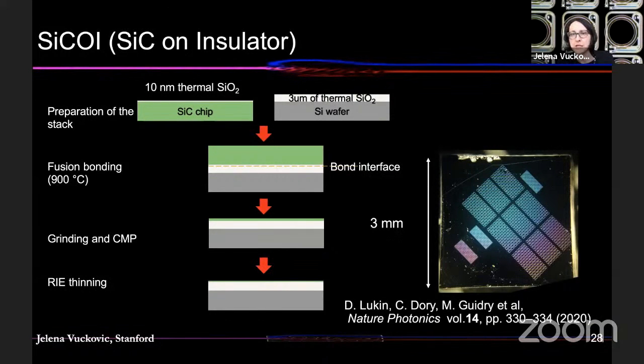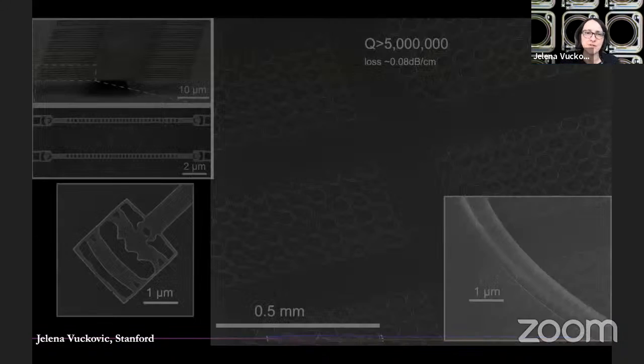If you try to repeat the same process that people use to make silicon on insulator, which is the so-called smart cut process with ion implantation and lifting off films and transferring, and we spent 2 years doing that, it doesn't work because you have to bombard with ions, and that introduces unintentional defects, or it affects the structure and degrades it for quantum optics.